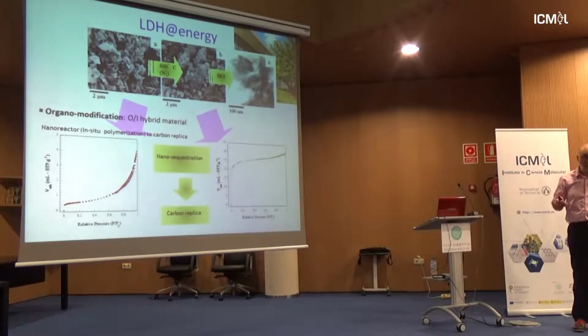I will cover very briefly what we have done in the past in terms of LDH and energy, because it's not obvious to use LDH platelets or composites for energy. At first, we used layered double hydroxide for the confinement of organic species that can produce carbon during carbonization, because you use the confinement of the layered structure to yield carbon. Why is it of interest? Because you confine the carbon species and you get a macroporous carbon. So when you do so, you have, for instance, styrene benzene sulfonic acid with zinc aluminum.